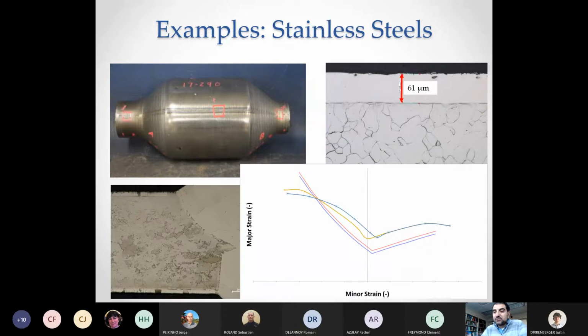So we spent a lot of time looking at methods of welding this material, because if you are not careful, you weld the material and then you lose this chromium layer on the outside, and then corrosion will happen right along the weld. So we had to come up with the right welding method and the right filler to use here, and we had to make sure that there was no gap in the chromium layer on the outside that would cause this material to fail.